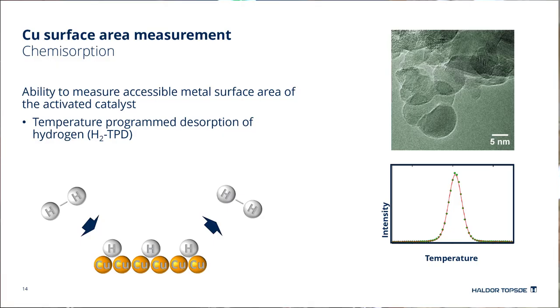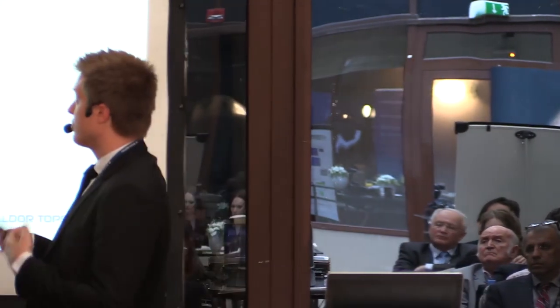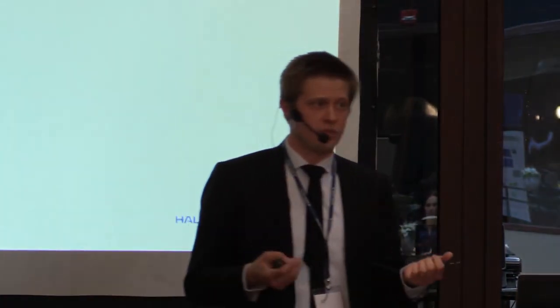In the fixed bed reactor system, we had some chemisorption methods available, and these methods are really good at probing the exposed copper surface area. So they can give you a measure of the surface area of your catalyst, but only the surface area which is exposed to the gas phase.